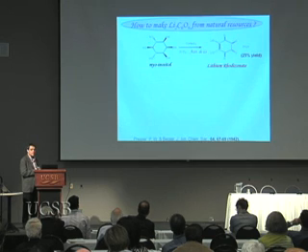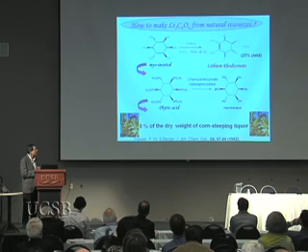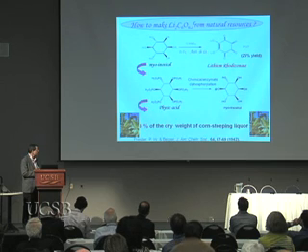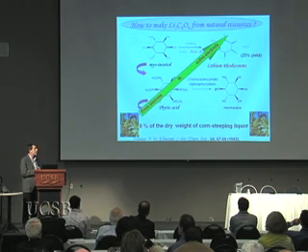But the most spectacular result is the fact that these compounds can be made from natural resources. This is a molecule that we are using. This molecule can be made via some kind of chemical reaction from some kind of carbohydrate. And this carbohydrate, as indicated here, can be obtained from phytic acid, which is really a byproduct or product that you can find distributed in a lot of plants and, for instance, constitutes 8% of the dry weight of corn steep liquor. So this means that we can really go from biomass to active electrode materials.